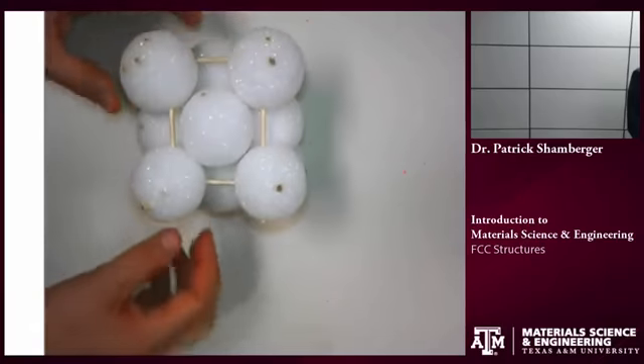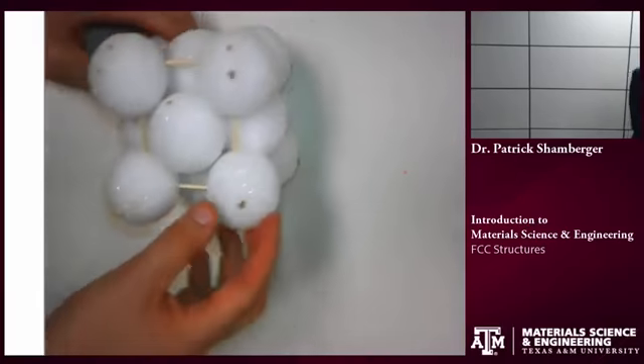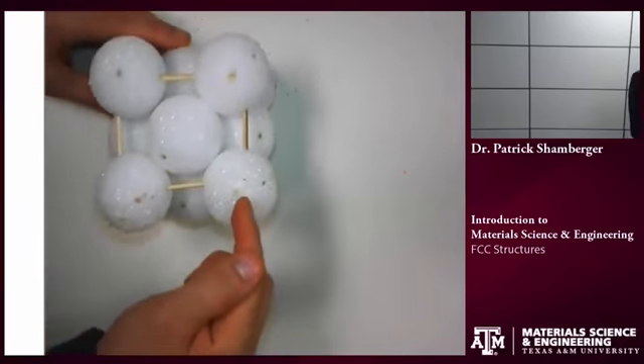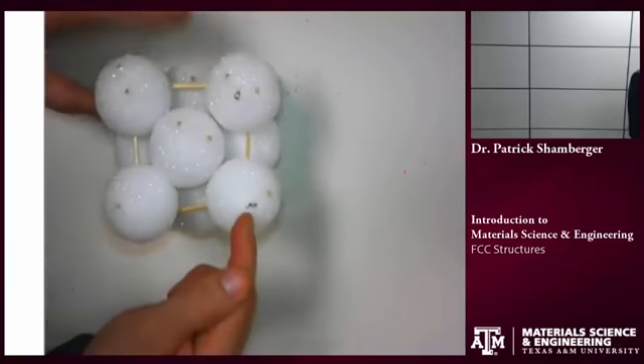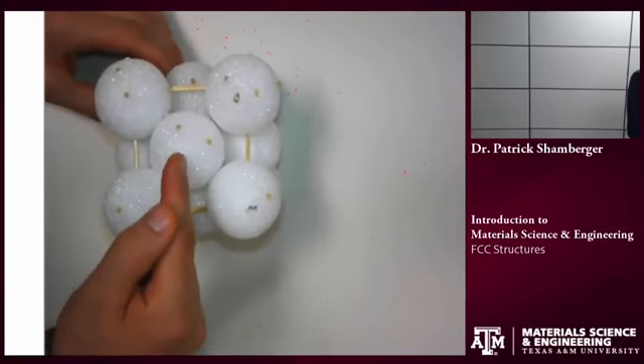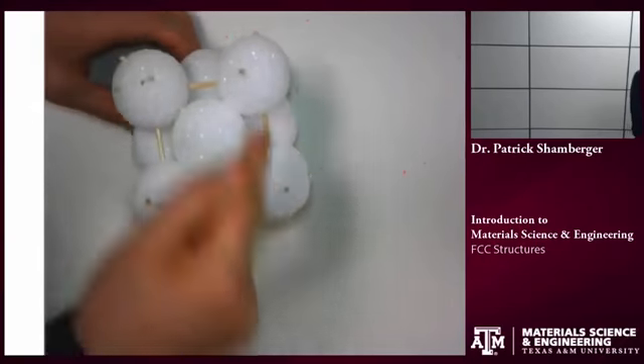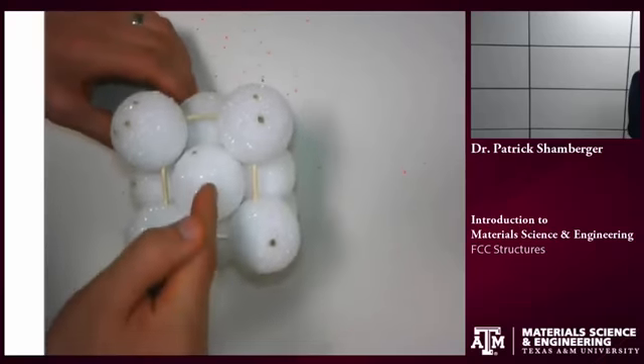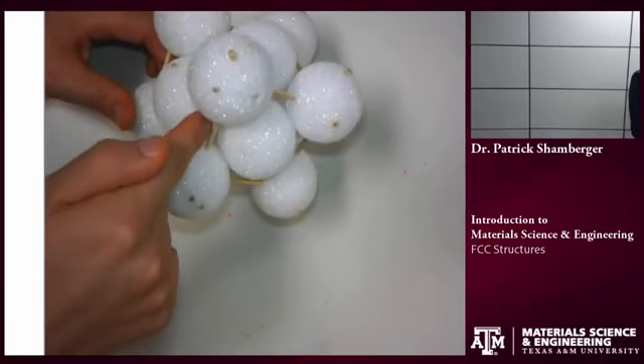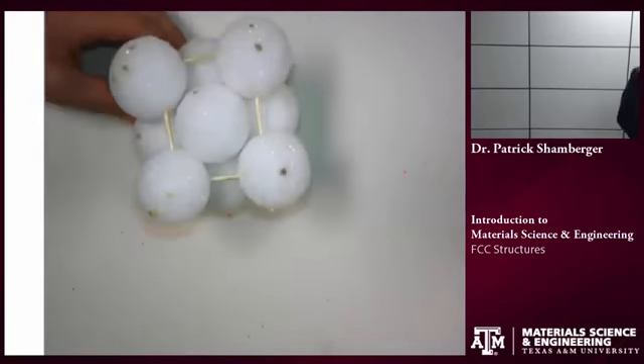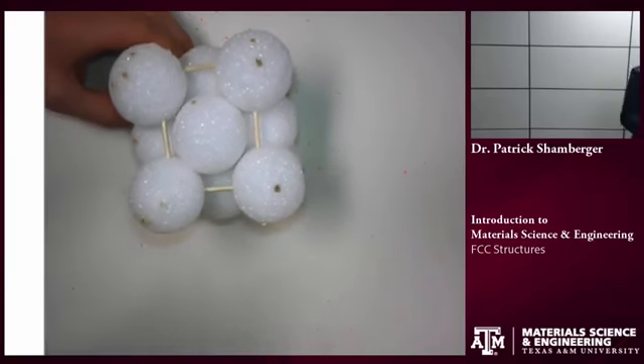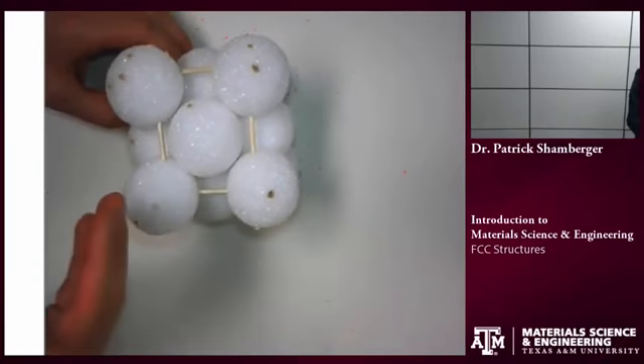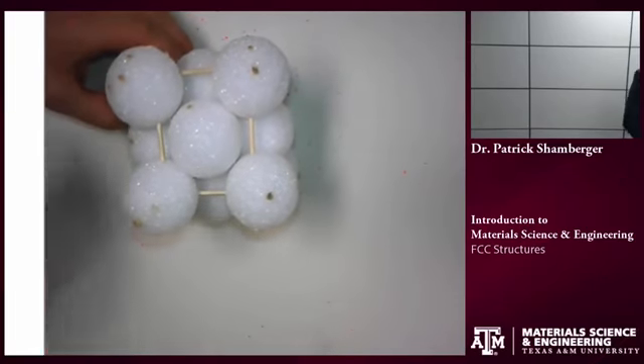The face-centered cubic Bravais lattice is defined by a cube that has one lattice point on each corner and one lattice point in the center of each of the faces of the cube. There's no lattice point in the very center of this cube. Remember, the definition of a lattice point is that its surroundings are entirely equivalent to every other lattice point.